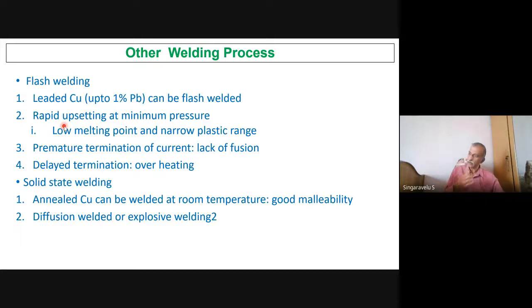Yesterday we told that for high strength low alloy steel, pressure has to be increased. Here you have to go for the minimum pressure. Low melting point and narrow plastic range. Premature termination of the current results in lack of fusion. Delayed termination will lead to overheating. The parameter setting is very critical.